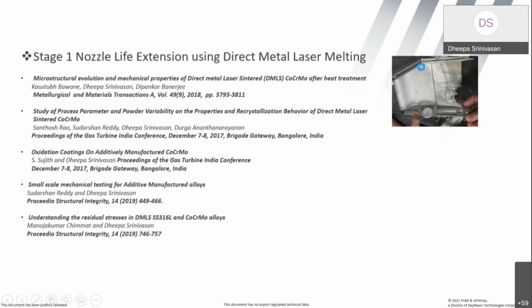The other thing we said, let us also use direct energy deposition, laser DED, and cut off this damaged part again, and let us build on top of the existing nozzle, because this portion seems to be quite good near the trailing edge. Let us build using direct laser deposition the part to the near net shape with all the cooling holes and so on. So fortunately, during that 1 year, at least 4 master students between 2015 to 17 worked with me, and some of the work we've been able to present in some conference proceedings and some publications, and that is what I'm sharing here.